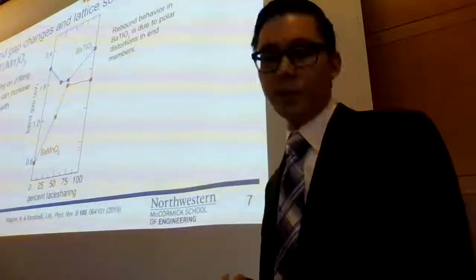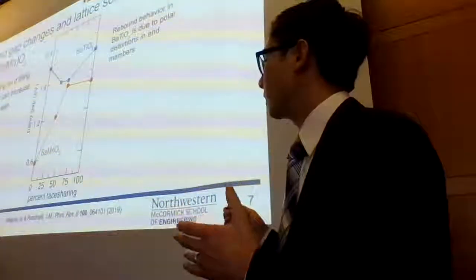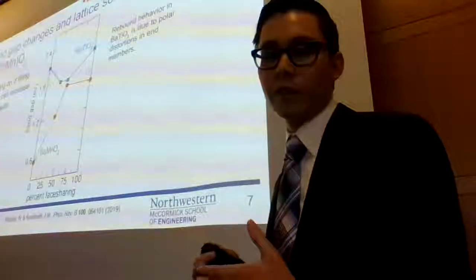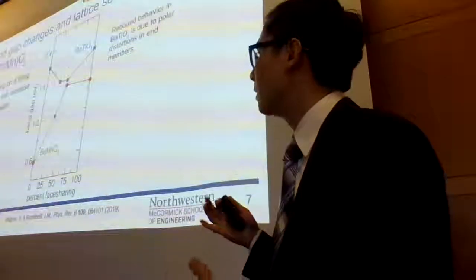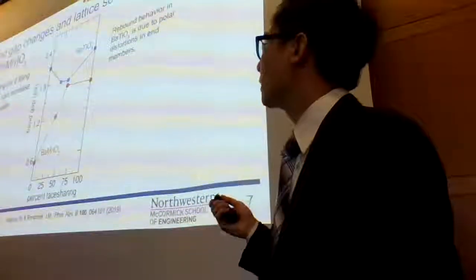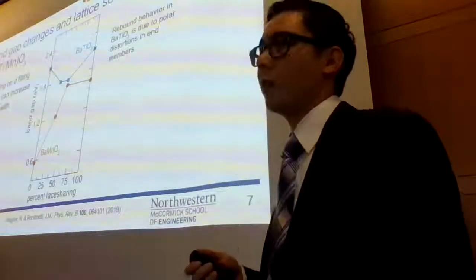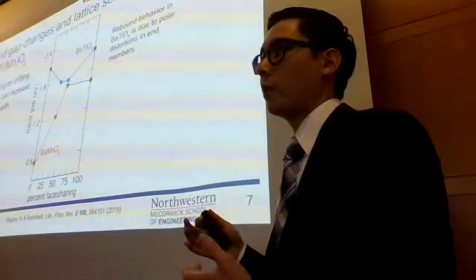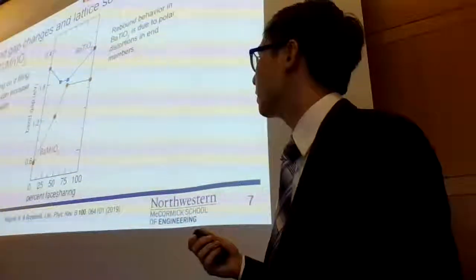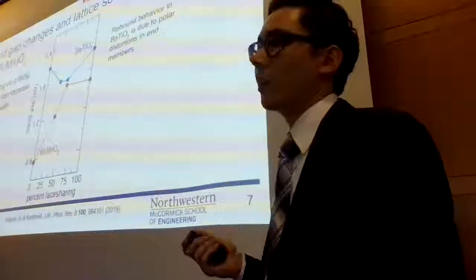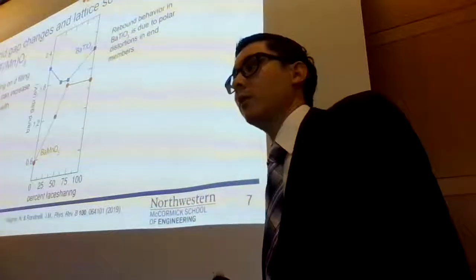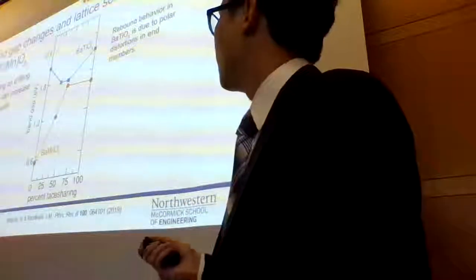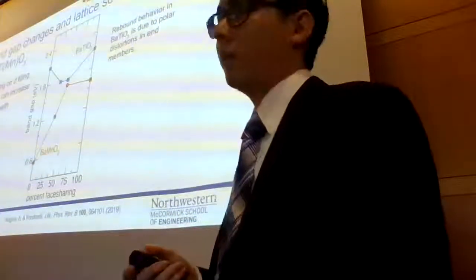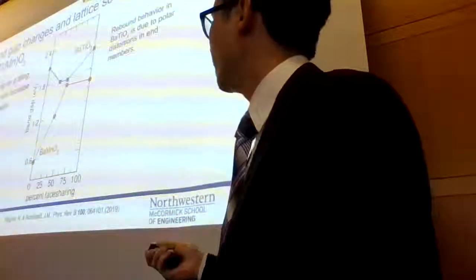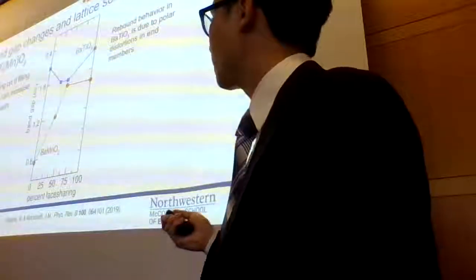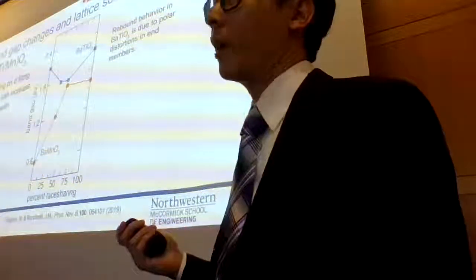So one of the first things I'd like to talk about is just a basic question: as you change the percent face sharing of this structure, or these polymorphs, looking at two prototypical compositions, barium titanate, which is also known to have both cubic corner sharing structures as well as a face sharing analog at high pressure, what the effect is on the electronic band gap of this material, so the energy required to excite an electron from the valence band to the conduction band. And we can actually see for barium manganite, there's changes on the order of several hundred meV going from the cubic corner connected structure up to this face sharing analog.